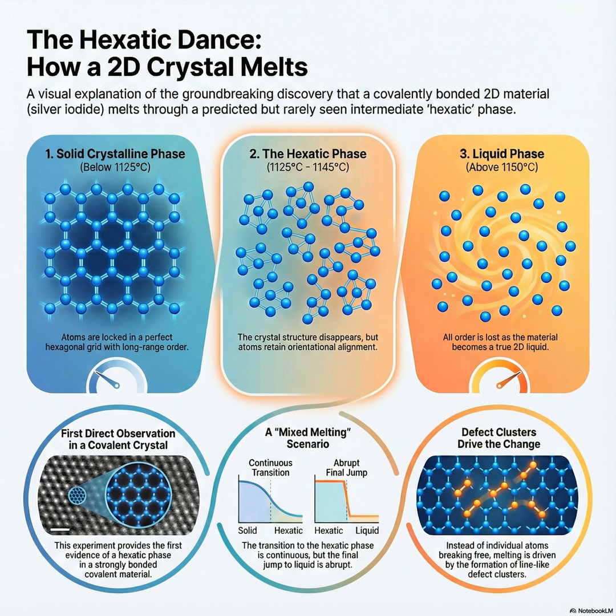And they could measure that by looking at the local density distribution of the particles. Yes. They essentially mapped the particle density across the material and plotted it on a histogram. If the transition is continuous, you should see a unimodal distribution. Meaning one peak. One single peak that just gradually shifts. Imagine a graph with one smooth hill that just moves from left to right. And that's what they saw during the solid to hexatic transition. But once the temperature hit that final melting range from hexatic to liquid, the plot changed.